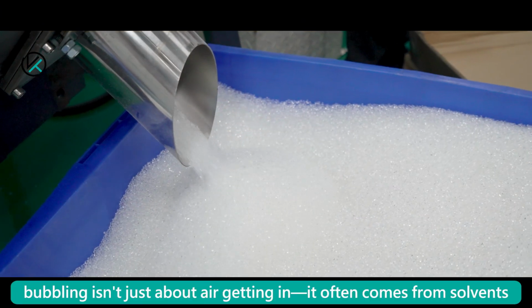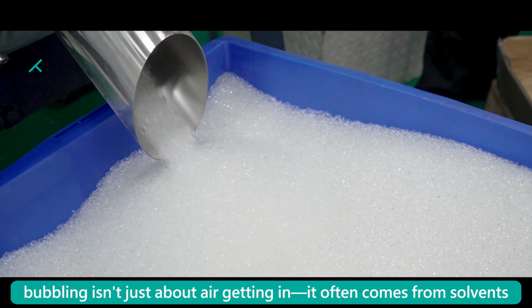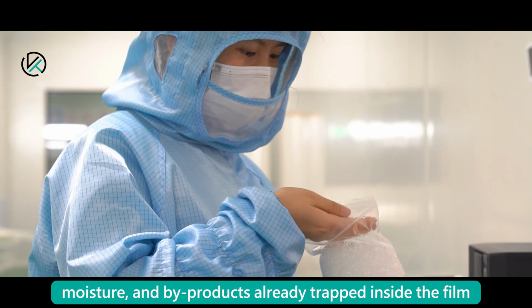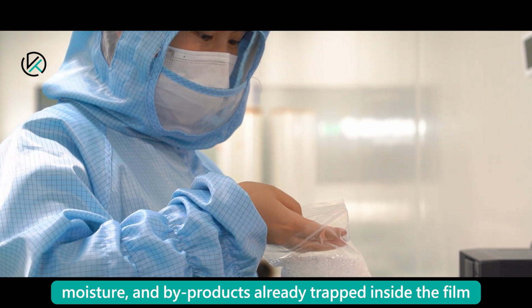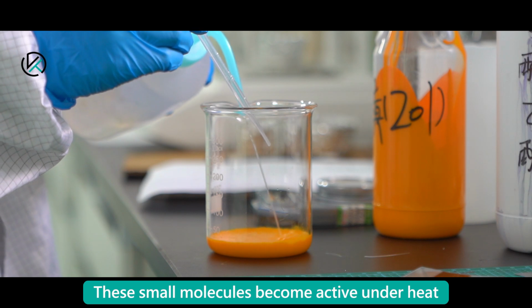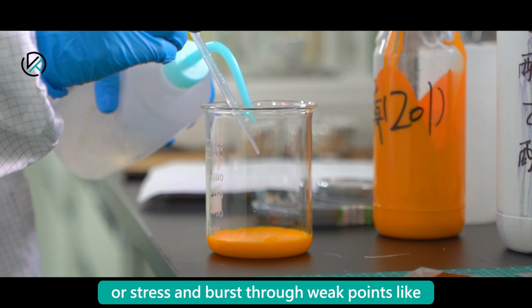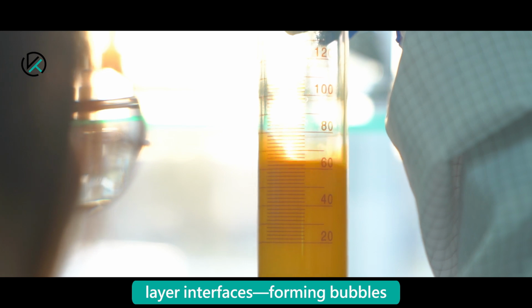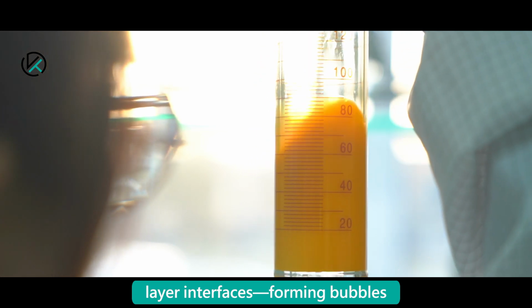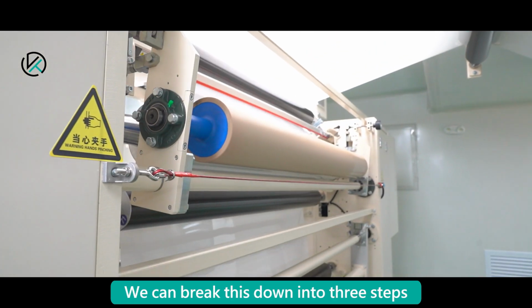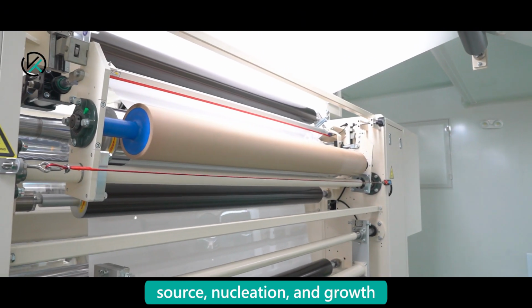In fact, bubbling isn't just about air getting in. It often comes from solvents, moisture, and byproducts already trapped inside the film. These small molecules become active under heat or stress and burst through weak points like layer interfaces, forming bubbles. We can break this down into 3 steps: source, nucleation, and growth.